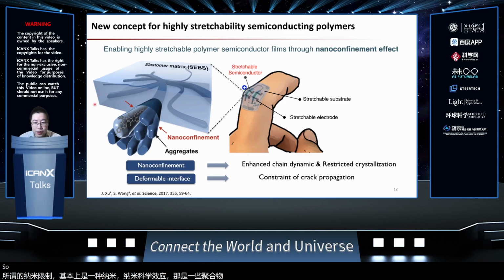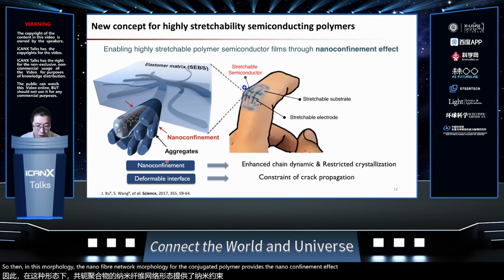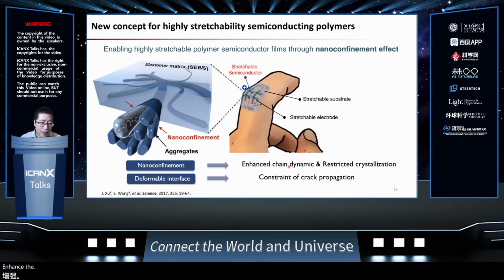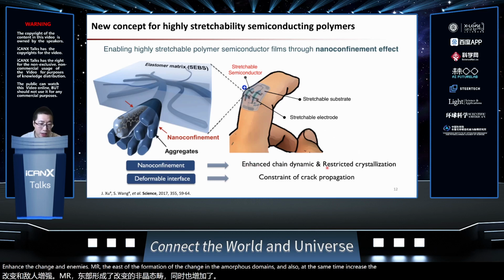So the way this works for our purpose is we can design this type of morphology that has a nanofiber interconnected network based on this conjugated polymer, semiconducting polymer, and then embed it in a soft elastomer matrix. In this nanofiber network morphology, the conjugated polymer provides the nano confinement effect, which acts to enhance the chain dynamics, meaning the ease of deformation of the chains in the amorphous domain, and also at the same time increases the percentage of the amorphous domain by restricting the crystallization.